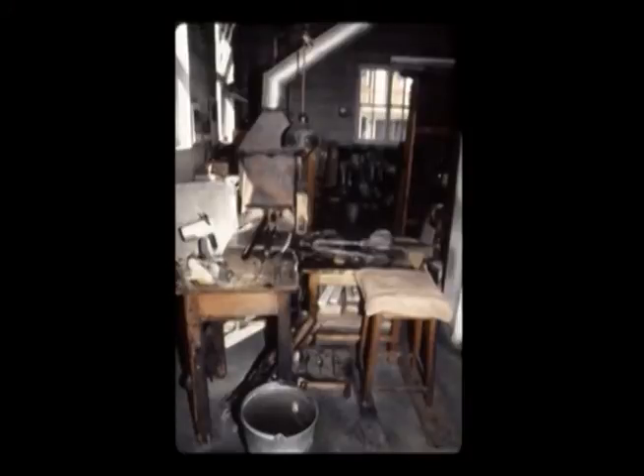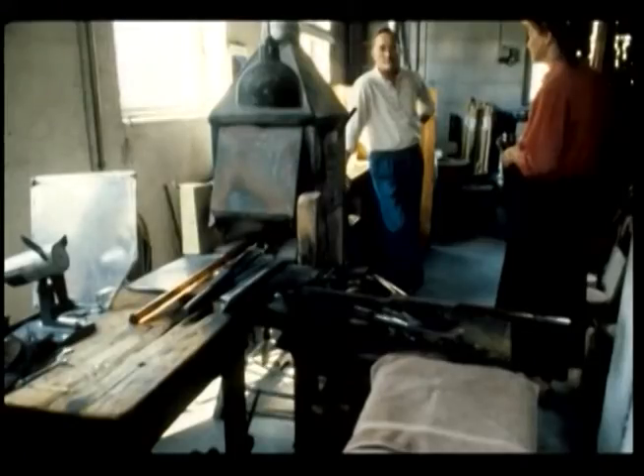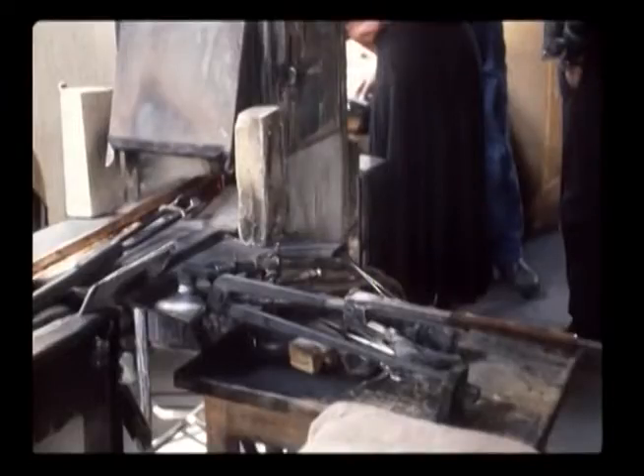This factory in Germany still had one of these old tongs in use. It was like seeing something out of a museum. The worker would sit on the right, and the chimney to the left heats the glass rods. A very labor-intensive, slow process. When they shut down at the end of the day, they put the beads in an earthenware pot inside this chimney to cool. That's how they're annealed.